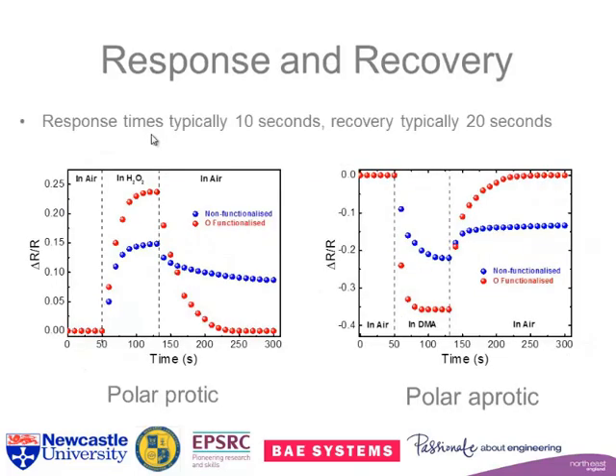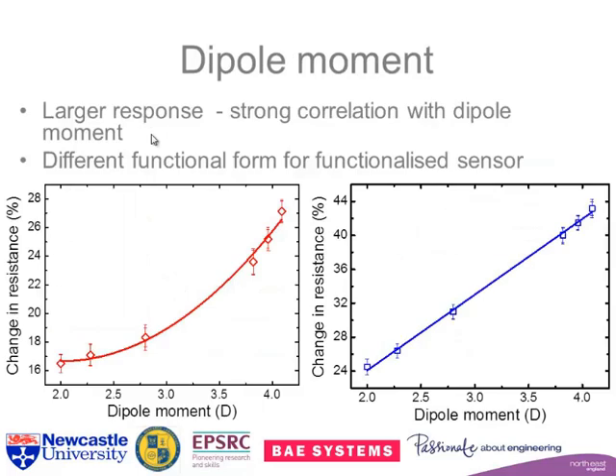So response and recovery, well, if we take a comparison between non-functionalized blue and the oxygen functionalized, 2 things to see. 1, we see an enhanced response. 2, we get a full recovery. So that's hydrogen peroxide, that's polar protic, and on this side is dimethyl anhydride, I think it is. Again, we see a larger response, and we see a full recovery. So by changing the surface of our material, we actually now can recover, as well as having a larger response.